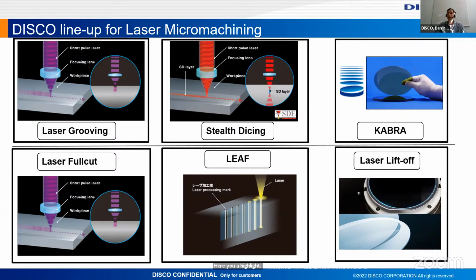More or less the idea here is to focus inside the material, do a modification, do many of these modifications along your separation line, and then later on by applying an external stress, you can separate the wafer. We also have KABRA, which addresses the wide bandgap wafer production. I will have a dedicated slide on that at the end, so I will come back to that later.